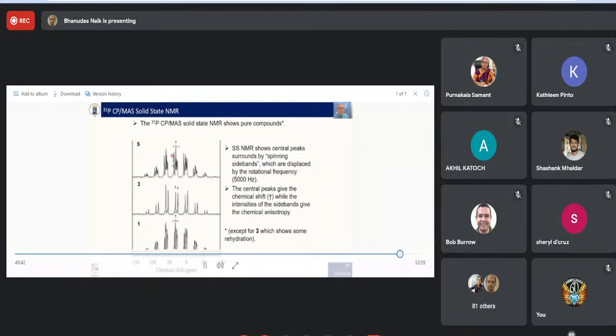So the center peaks are the principal peaks here, and you have the spinning side bands, which are coming out on the sides here. So this is the center peak of interest, and the spinning side bands are coming out here on the side. The spinning side bands are really quite important because you can model these spectra and determine the chemical shielding tensors of these peaks as well. So you can actually get more information from the solid state than the liquid.